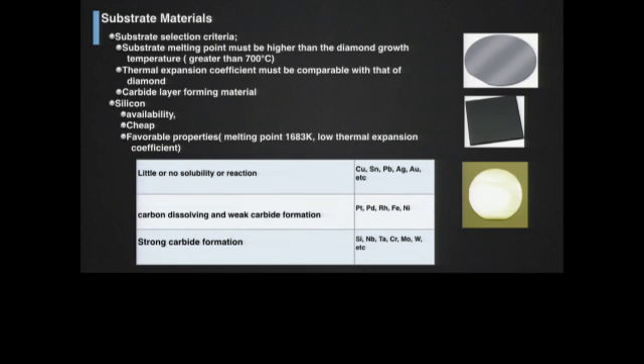So here are some of the things that we considered: little or no solubility or reaction with the diamond, carbon dissolving and weak carbide formation, strong carbide formation. So we looked at a whole bunch of different substrates, not only their chemical makeup, but their crystalline structure as well, to see if we could mix and match some of those substrates so that we might have a chance of epitaxially growing high quality diamond on some foreign substrates.